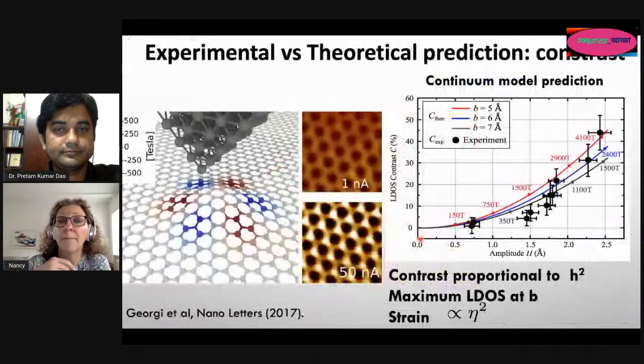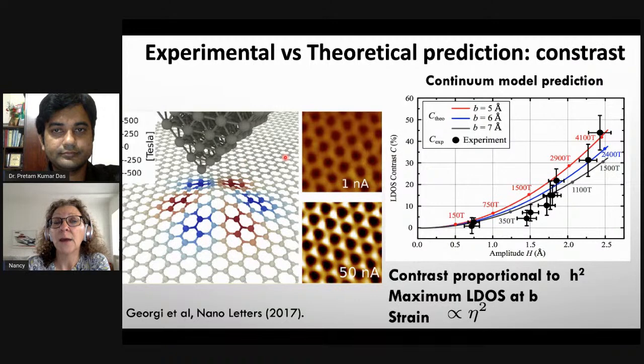And that is what happens in these experiments, where the tip is precisely measuring or taking images on one side of the bubble. And that's why, while in the flat regions you expect to see perfect hexagonal images, on one side of the bubble you start seeing only triangular regions.